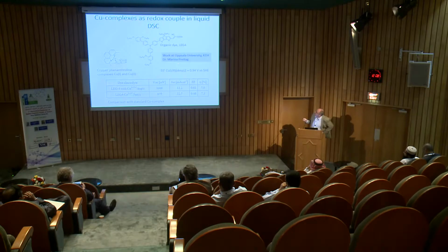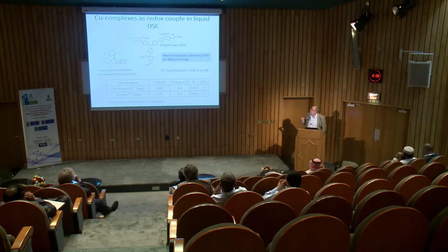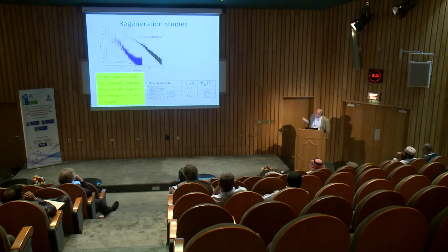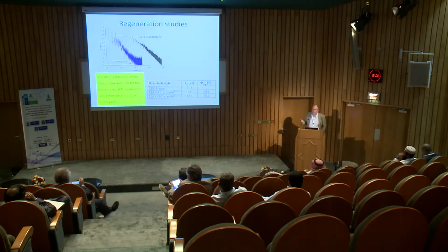It's a postdoc of mine, Marina Freitag, who started in Uppsala and continues now at EPFL. It's a copper phenanthroline redox system, with the organic dye, and we have similar efficiency as the cobalt system, about 7%, so that's good news. We have very high voltage with the copper phenanthroline, higher than the cobalt, about 1 volt. So that indicates to us that we can have a positive redox potential, and this is very positive. The regeneration now we can use is exactly the 0.2 volt we are looking for. We can regenerate the dye with the driving force of only 0.2 volt and 100% regeneration. So here now we think we have reached a target redox system and dye where we can explore further.